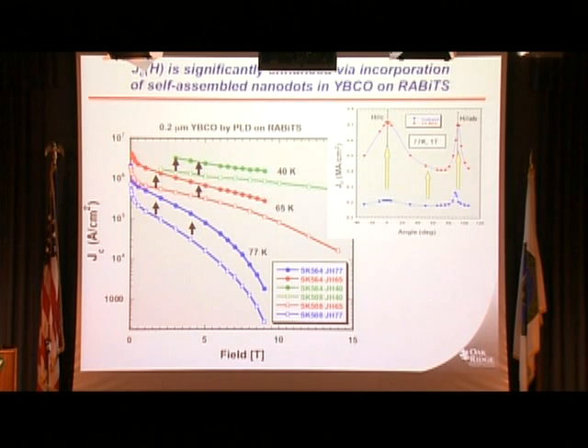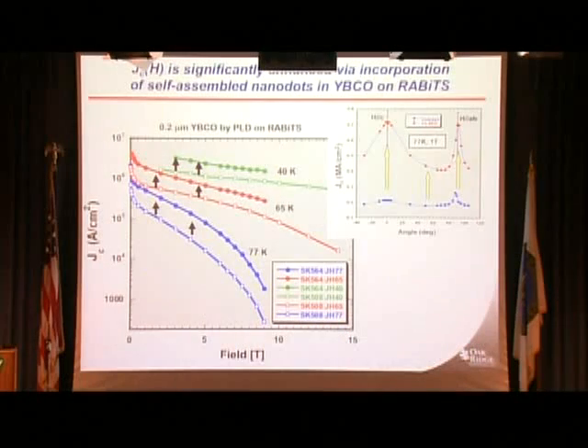all the open circles here, in all these measurement temperature regimes of 3 different temperatures, are without these columns and the filled ones are with these columns. And you can see that there's a massive enhancement at all magnetic fields and measurement temperatures. And if you look at the angular dependence, that's the amount of current that you can pass as a function of applied field, you can see that without these and with these, there's a massive enhancement.